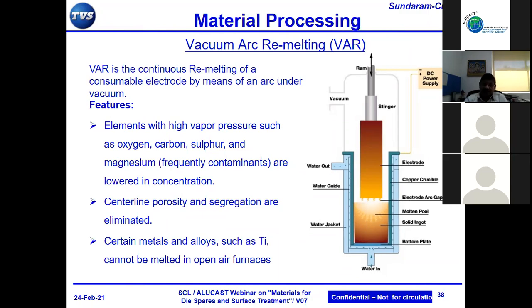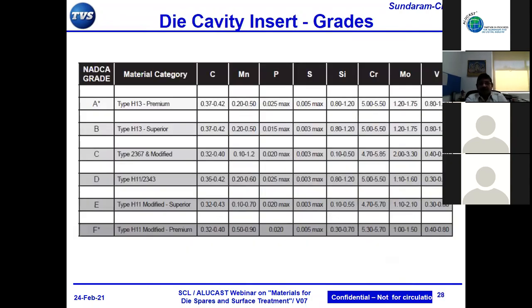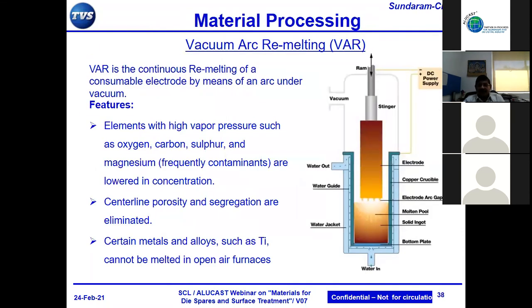And with this kind of chemical composition, what we are talking in terms of molybdenum up to 1.75%, vanadium up to 1.2%, and chromium with 5%, given the kind of density differences, when we have a large metal pool which is solidifying slowly twice, once in ESR and the second time in VAR, the kind of segregations that happen limits our melting process to a maximum of 800 dia, unless lots of innovations in the solidification process happen, which will add to the cost of processing.